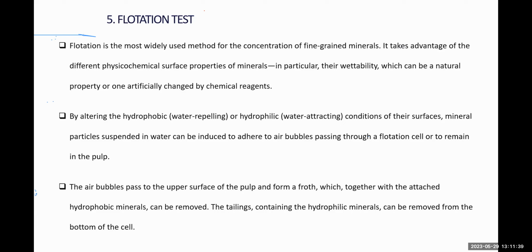How do you activate? You activate it using a basic media. The solution must be basic. So we use sodium hydroxide, caustic soda, to create this basic environment for this flotation to take place. For lepidolite, there is no activation. But for spodumene, we have to activate it with sodium hydroxide. We have a dose of sodium hydroxide to activate it.